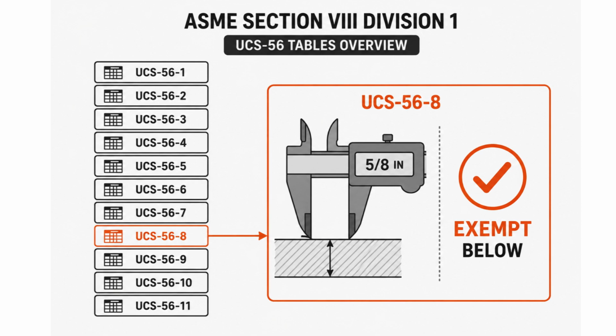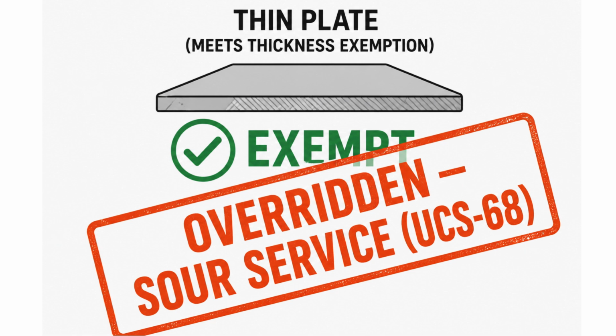The exemptions themselves live in 11 separate tables, UCS-56-1 through UCS-56-11, one for each material group, and each table sets its own thickness threshold below which PWHT isn't mandatory. For ordinary P number 1 carbon steel, that threshold commonly lands around 5/8 of an inch. Thinner than that, you are often exempt. Thicker, PWHT applies.